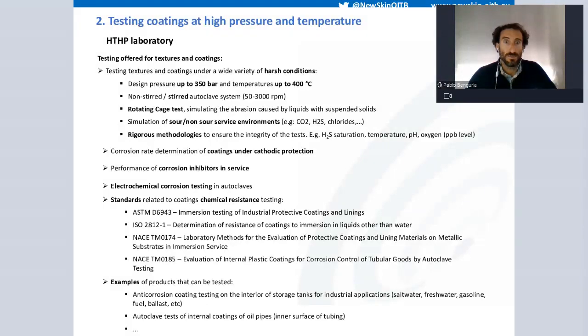Well, we can simulate a wide range of service environments with CO2, sulfides, chlorides, and so on. We then determine the corrosion rates, even under cathodic protection. We can also test the performance of corrosion inhibitors in service. We are accredited in several standards that you can see there. And some of the examples of products that can be tested here are anti-corrosion coating testing of storage tanks for industrial applications, for example, or autoclave tests of internal coatings for oil pipes, for example.